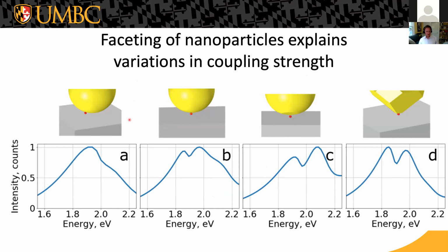And the important thing here is that if we take a sphere, and we put a quantum dot close to the gap, we really don't see any significant change in the scattering spectrum. And even if we do put the quantum dot in the right location between a gold sphere and the silver surface, we saw only a relatively modest induced transparency, and we certainly do not get into the strong coupling regime. And the reason for this, of course, is that those gold particles aren't really spheres, right? If you synthesize or purchase gold nanospheres, most of the time you're not actually getting spherical particles, you're getting these highly faceted particles like you saw in that electron microscope image. They're a cubic lattice and they don't like to be round.